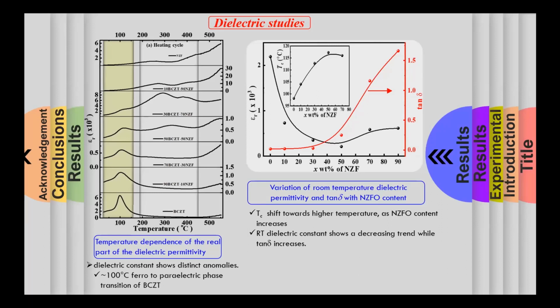Because if we take those ferroelectric compounds which are displacive, the ones which are the most popular and most observable, then we don't get a magnetic response at room temperature, but well below room temperature. So from an application point of view, it will not be very useful for us. But maybe, who knows, in future you may find, or I can find.